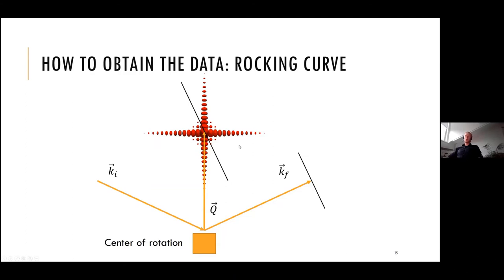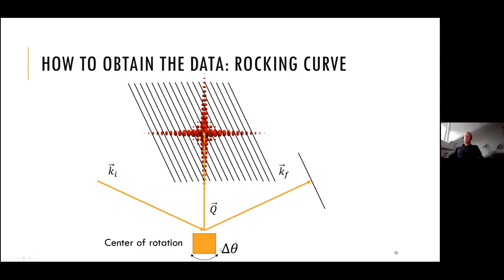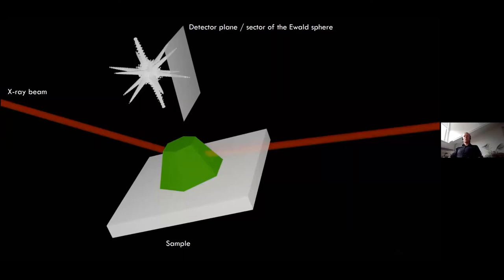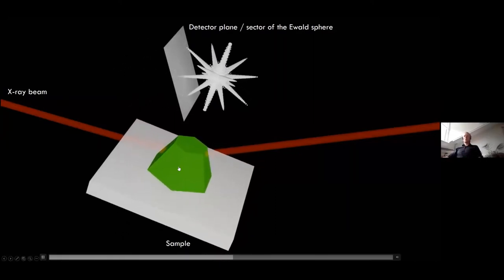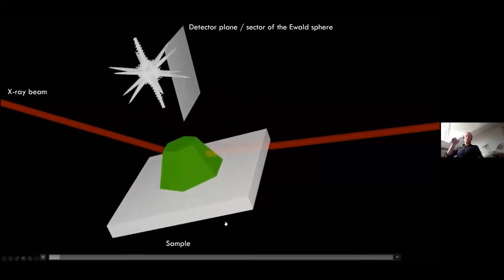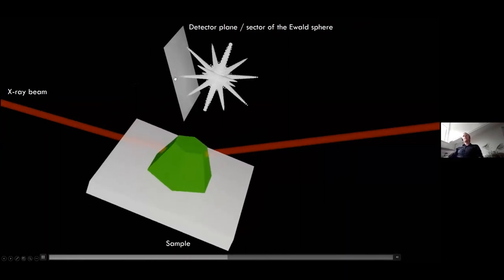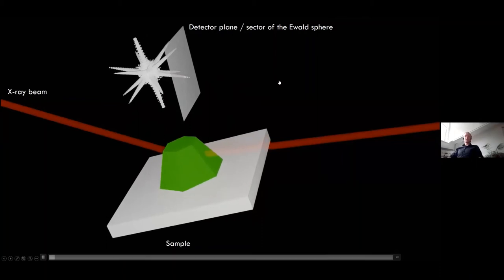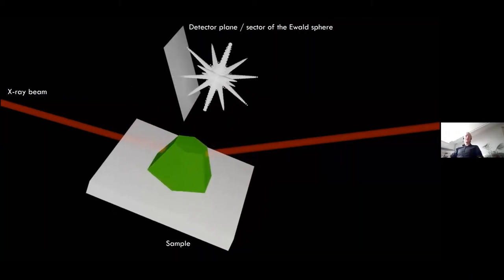So this plane represents the detector, which is analogous to a small arc in the Ewald sphere formation. And it crosses the Bragg point if you align your crystal to the Bragg condition. And then by mechanically rotating your sample by small steps with the angle delta theta, you can actually get these slices through the reciprocal space and record the full three-dimensional distribution of intensity around the Bragg point. This is actually one of the fastest and easiest ways to record Bragg CDI data. And to see it in a more intuitive way, this is an animation of how it actually happens. So the X-ray beam hits the sample, and when you do this nice tilting around the Bragg condition, the reciprocal space travels through the detector plane, and you record each of these slices on your detector, and you can work with this data later on.